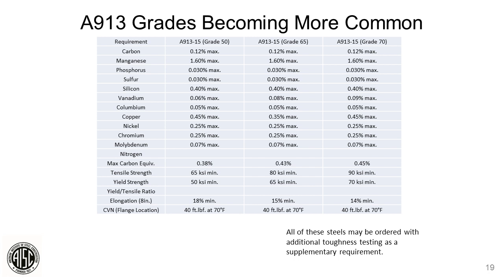Copper's all right, about 0.45. And the residuals are also restricted. But as you go all the way down to the bottom where it says max carbon equivalency, towards the bottom third there, you can see where the weldability of steel comes into play. And this is actually set by specification, a 0.38, a 0.43, and a 0.45. So as you see the strength goes up, we have to bump the CE up a little bit.